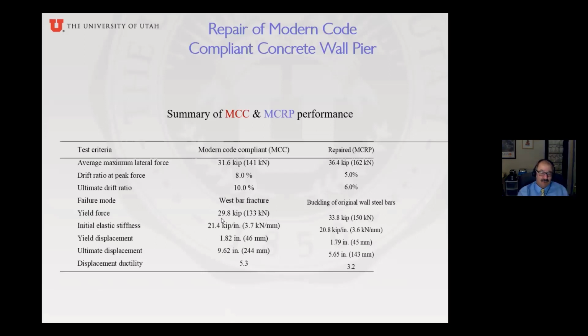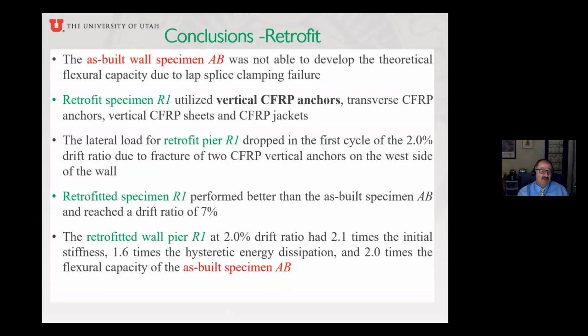Yield force was 30. Here it was 34. Stiffness was 21. Here it's less, 20.8. Yield displacement about the same, 1.8 inches. Ultimate displacement was 9.6 here, 5.6 here. Ductility 5.3 here, 3.2. So I would say this was a good repair.